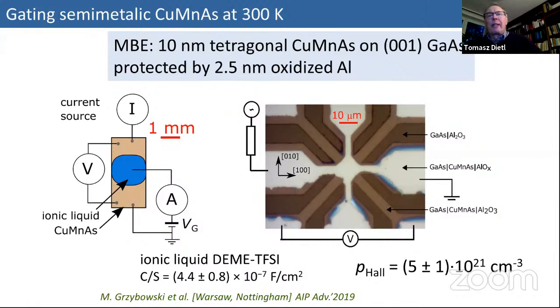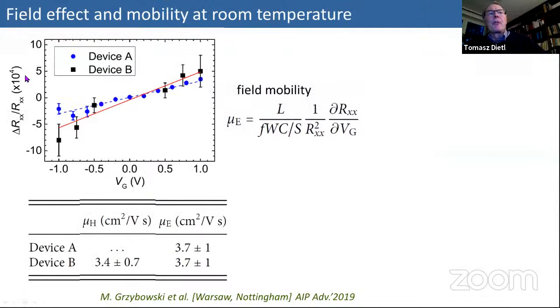So what he was measuring is what we call field effect, how resistance changes. Of course, these changes of resistance, which you expect, are not very large because it's a semi-metal. You can change carrier density, but of course you have a very large background density. It's a semi-metal, not a semiconductor. He managed to measure this change of resistance at the level of 0.1%, from which he was able to determine the field effect mobility.